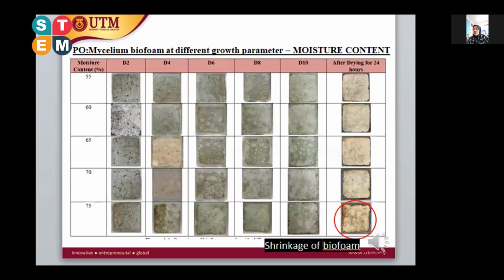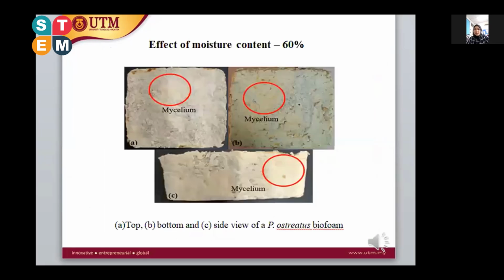Next. So this figure also shows the appearance of biofoam from PO at different moisture content. After drying for 24 hours, we can see that a moisture content over 75% has produced a shrinkage of biofoam, which means that high moisture content could shrink the biofoam.